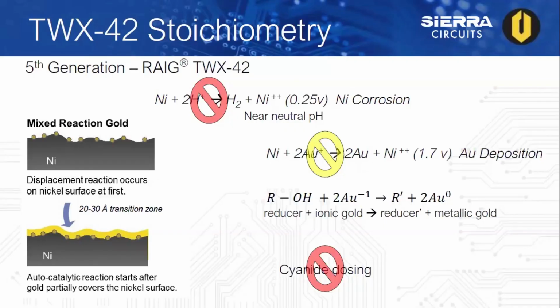A benefit of this bath is not needing to complete cyanide dosing, as was the case with older generation gold baths. Regarding reliability, this bath is beneficial because it's near neutral and can avoid nickel corrosion. A benefit of RAIG baths is that they can be used with most conventional final finishes like ENIG and ENEPIG, as well as some advanced final finishes.